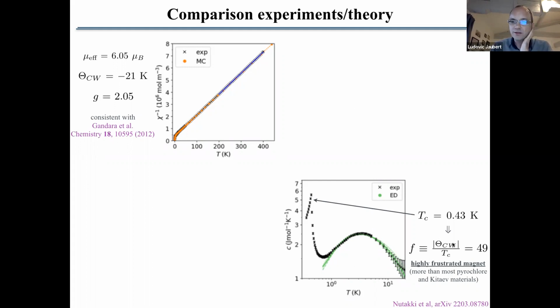And because the Curie-Weiss temperature tells you the strength of the nearest neighbor interactions, and TC gives you the value of the transition, you would expect a transition at the Curie-Weiss value, but you only get it at this much lower value. And so this ratio tells you it's a very highly frustrated system.